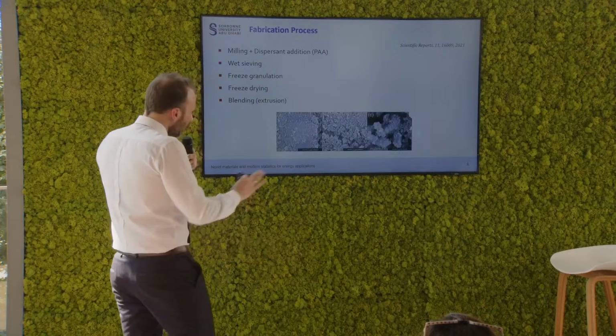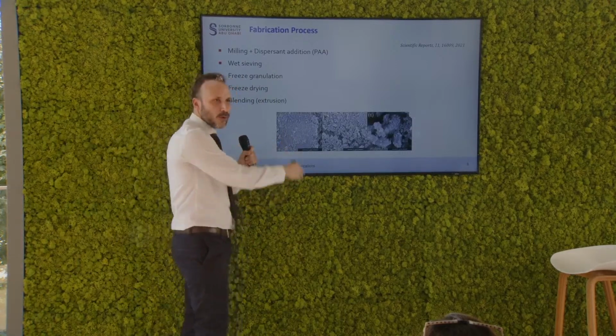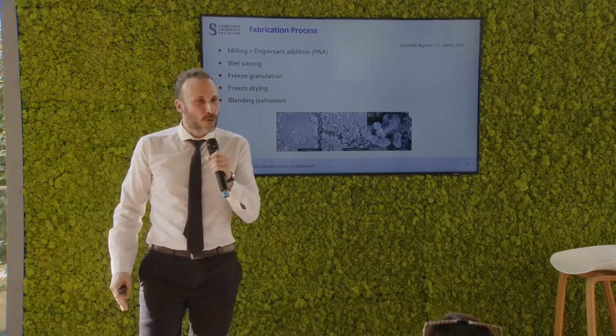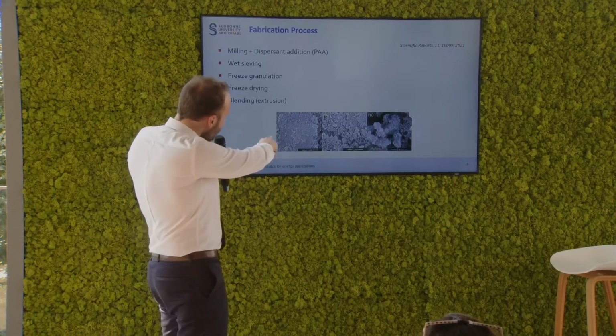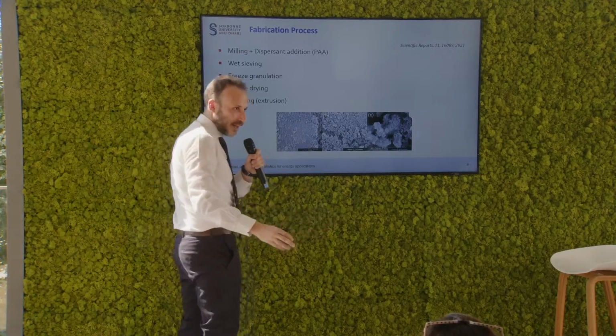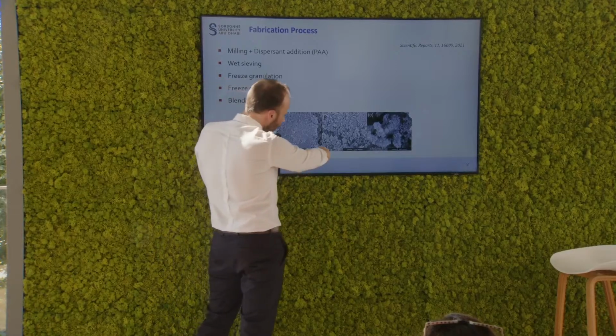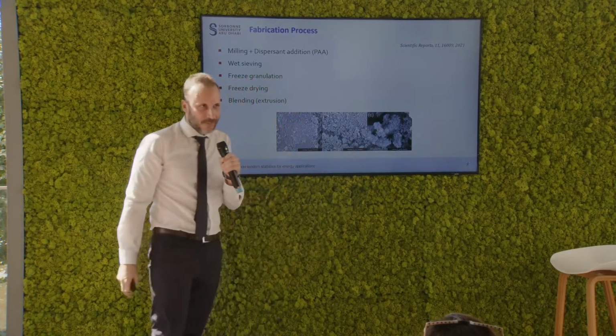Then the slurries, they look basically somehow like this. These are SEM images of the frozen granules for 3 different suspensions. I know you cannot see actually, so it's alumina silica, titania silica, and alumina titania.